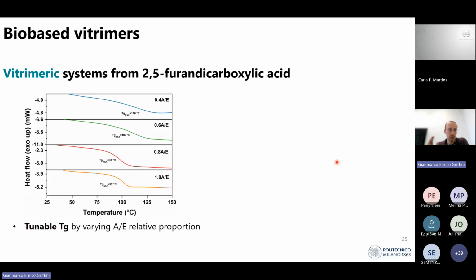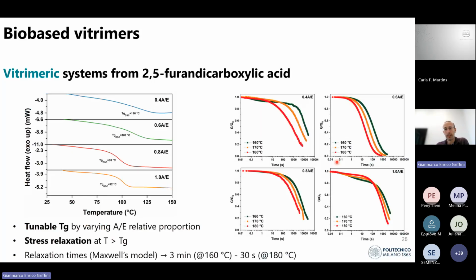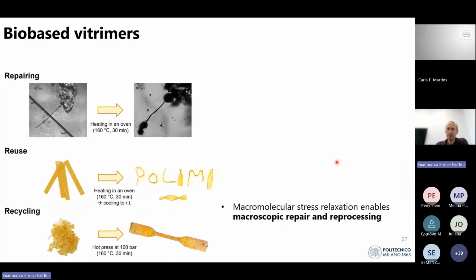So by, again, modulating the formulation, we could tune the glass transition temperature, which means tuning the operating window in terms of temperatures for those materials. And then we also studied the stress relaxation processes at temperatures higher than the glass transition temperature. And you see that we have relatively good relaxation for all the systems, which pretty well fits the Maxwell model, with relaxation times that are in line with typical systems based on analogous precursors.